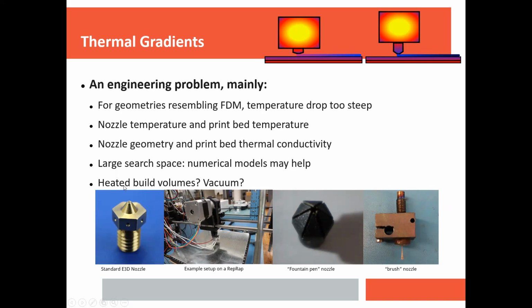Standard E3D nozzles are too thin at the tip. So even though brass is very conductive, by the time the metal reaches the tip here, it's already solidified. And that's what Lulzbot kept running into. And you can also use a fountain pen structure or a brush. You can use the geometry of your nozzle, which is inherently unlikely to undergo granular jamming. And you can engineer that as well to reduce the probability of granular jamming, to reduce its severity, and even to knock off material that nucleates on the walls of the extruder, depending. That's all surface chemistry.